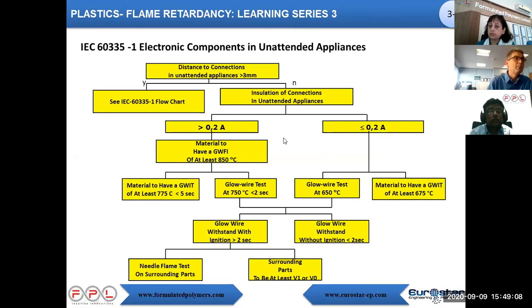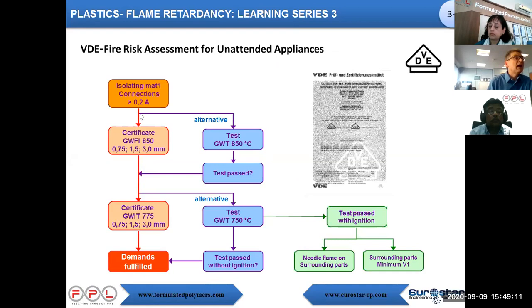We will take a bit more time on this slide with material having more energy, meaning more than 0.2 ampere. So you have two routes. Either you can make certification on testing on samples, or you can make it on part. If your material has a certificate GWFI 850 and a GWIT of 775 on samples, your demand is fulfilled. But you can test on part. In this case, you test at GWIT 850. If the test is passed and you have a certificate, you're done. Then, if you don't have a certificate, you can test on part, and if it passes without ignition, you are done.